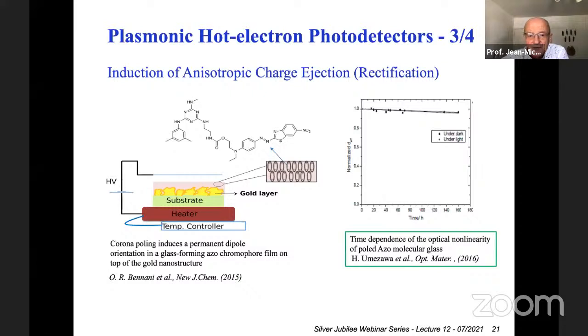In order to check that the photovoltage was created by hot electrons, and to vary the quantity of hot electrons that we could extract, we used a polarized layer of dipoles from nonlinear optical molecules. This Disperse Red, actually this azo dye, we knew it was nonlinear because it creates second harmonic generation and that it was stable under light. So we have second harmonic generation in that material, which is not a polymer, it's a molecular glass, which is quite stable under illumination. So we could pole the material by using corona poling with a wire and a heated substrate. And we have the layer of molecular glass on top of the gold layer. So we studied that phenomenon and then we monitored the hot electron emission from this.